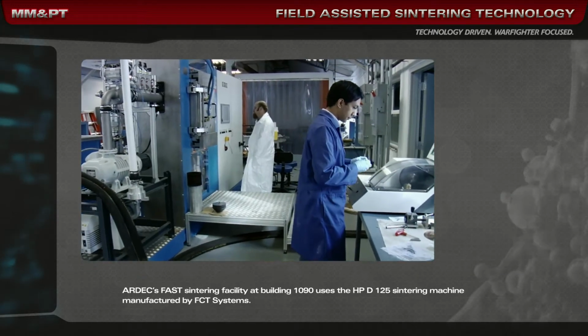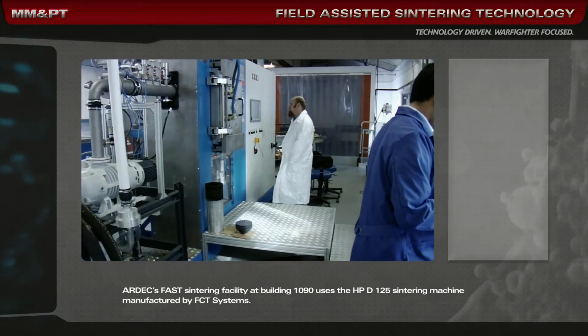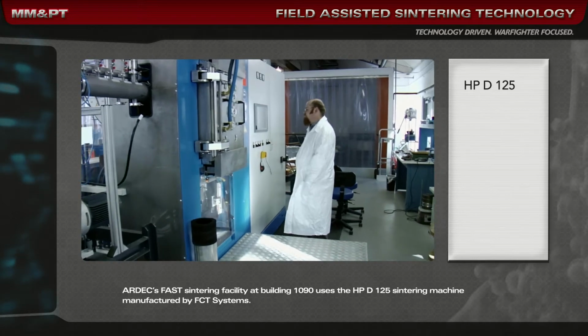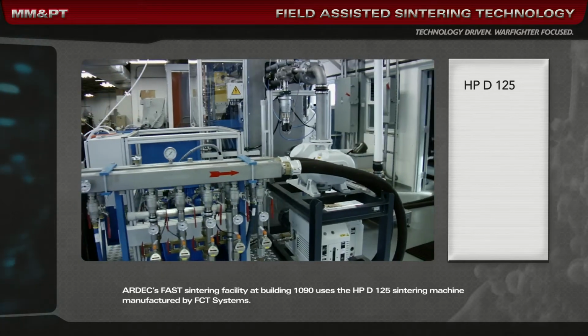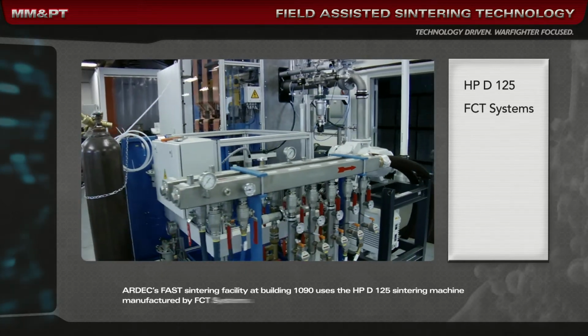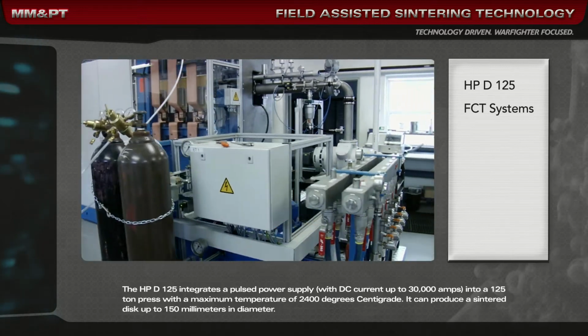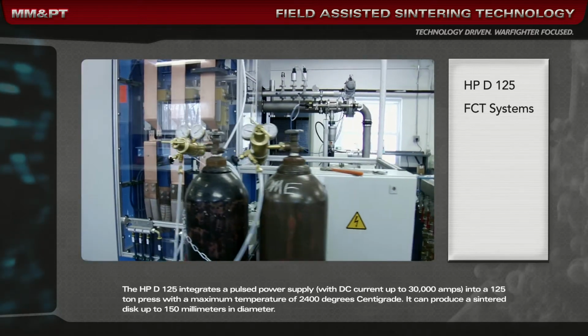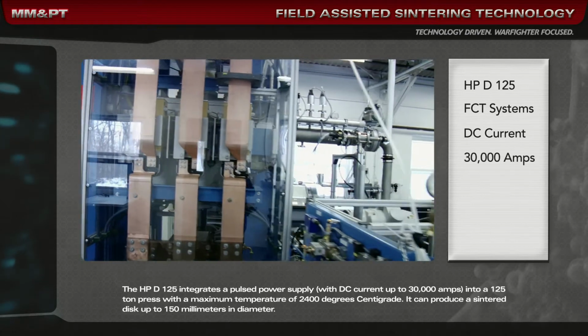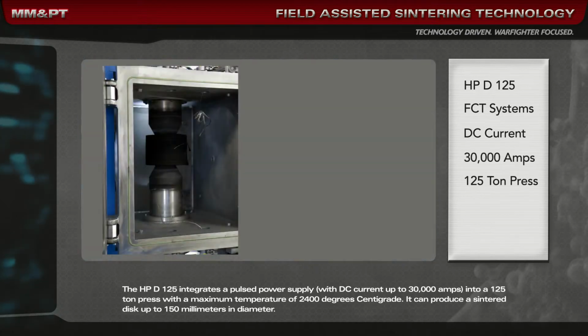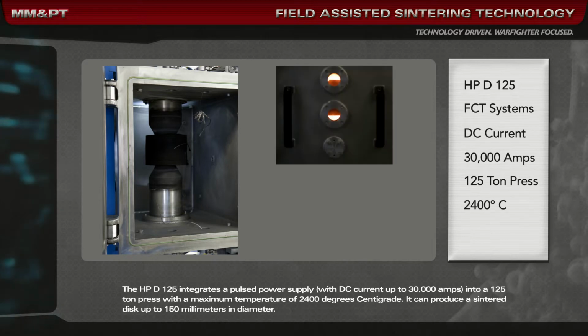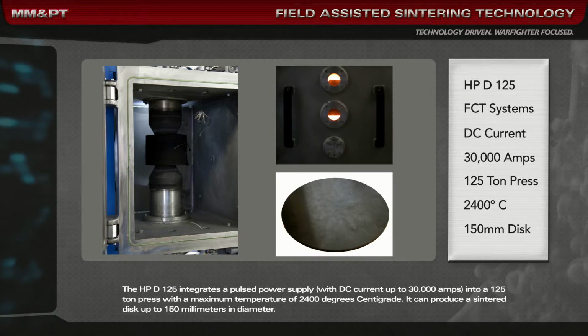ARDEC's FAST sintering facility at Building 1090 uses the HPD-125 sintering machine manufactured by FCT Systems. The HPD-125 integrates a pulsed power supply with DC current up to 30,000 amps into a 125-ton press with a maximum temperature of 2400 degrees centigrade. It can produce a sintered disc up to 150 millimeters in diameter.